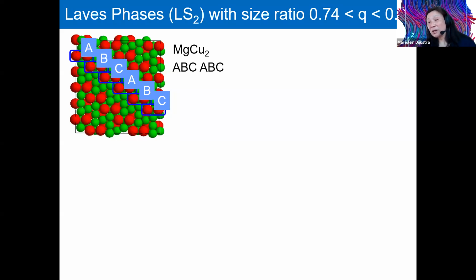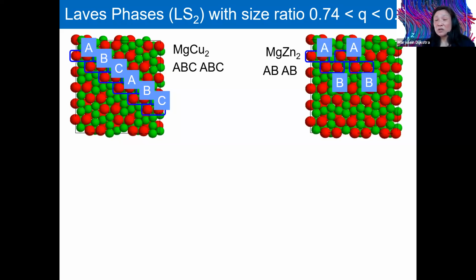So it's only entropy, no weird interactions, that drives these crystallizations or the self-assembly into these highly exotic structures. Another crystal structure that is very interesting are the so-called Laves phases. This is for a size ratio of about 0.7, 0.8. There are three types of Laves phases. The magnesium copper 2 phase, where the big spheres form a dimer, and these dimers are stacked in an ABC fashion.